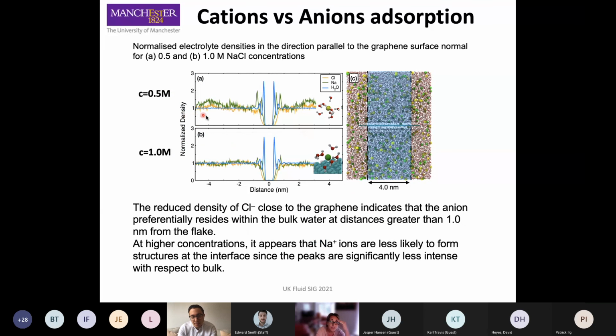Then with the procedure, we can actually run simulation for large systems with different concentration of the ions. So we focus on this initially with this sodium chloride electrolyte. And so we calculated, so this is the density profile of the ions. So here this is where the graphene is. And basically it's a mirror. So we have a graphene and then we have a reservoir of electrolyte on both sides.